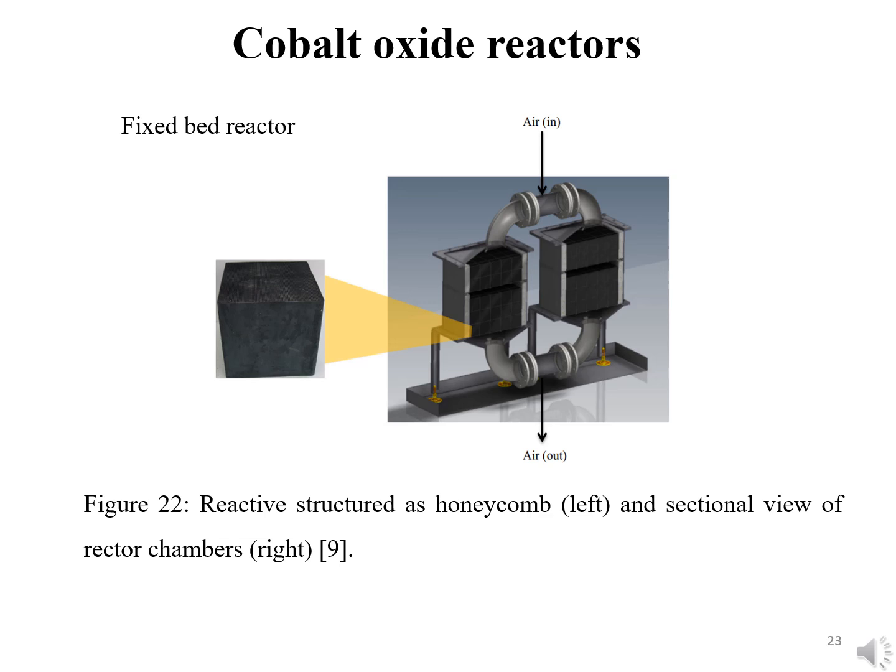According to several researchers, the mentioned problem can be solved by utilizing foam-shaped monoliths or structured honeycomb shape for the HTF to flow through. These honeycomb structures offer more surface area and effective heat transfer. The proposed arrangement has already undergone a lab-scale proof of concept validation that included semi-quantitative heat effects calculation and their association with redox processes and structural impacts during operation.